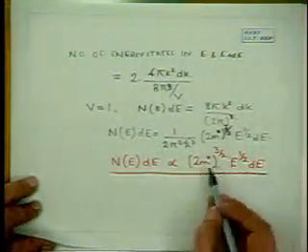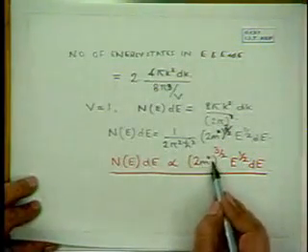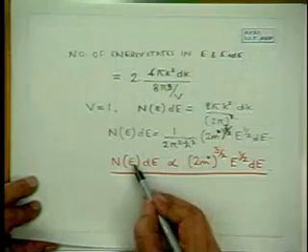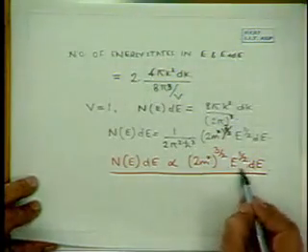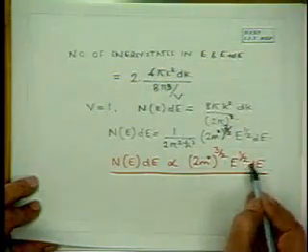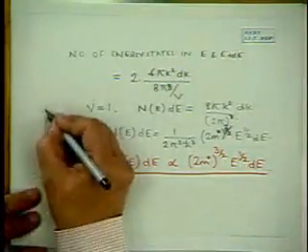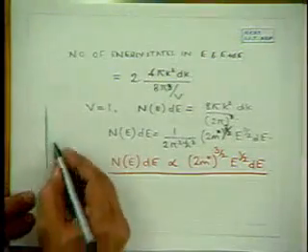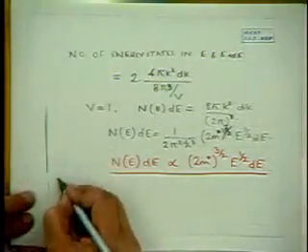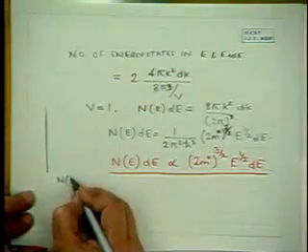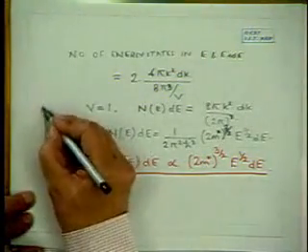The important part is that the density of states is proportional to the effective mass. So if you have a low effective mass, the density of states is low, and it goes as E to the power half dE. Right? So you want to depict the density of states Ne as a function of energy.